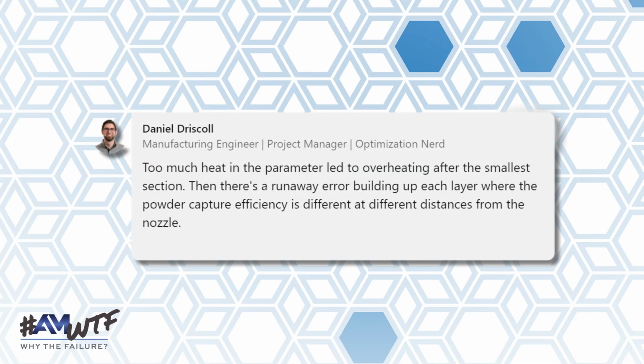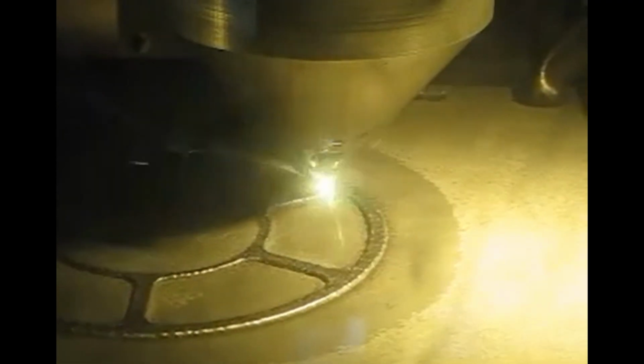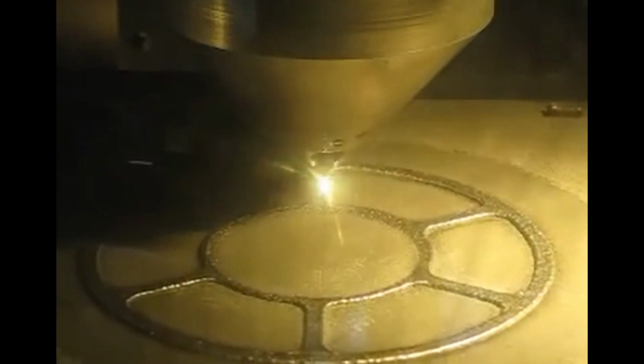All right. So in the social media conversation, is there a response that came really close? Yeah, I think Daniel Driscoll's response was probably the closest. He also noticed the runaway error of building up progressively from one layer to another and attributed it to powder capture efficiency. And I think that's really one of the things you can run into with DED that you don't with powder bed fusion. As you build up layers, the heating, the tool path, the melt pool size, all of that changes at each layer, depending on the thickness, the geometry, and those aspects, which then influences how much of the powder you're blowing in is captured in that melt pool. As it's going around and around, if that melt pool varies, then the amount of powder capture varies, which leads to differences and inconsistencies.